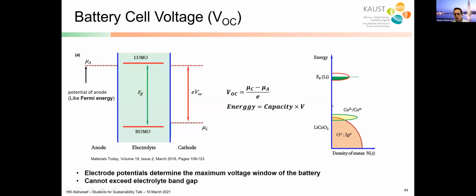And where this potential comes from for a given material, really for the physicists in the group, this comes from essentially the band structure, okay? And then for the chemist, maybe it's basically the oxidation potential for these with respect to the lithium ions. So you can actually nowadays simulate these structures, look at the density of states for the different orbitals in the oxide, and you can predict which one will have a higher potential and give a wider voltage window battery.